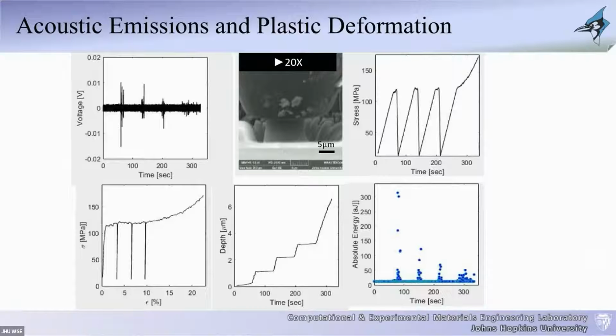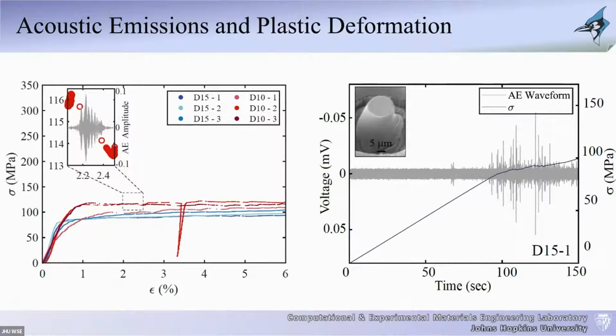But the neat thing with this type of experiment, let me show you a close-up of one of these experiments. So these are basically just representing different stress strain curves. If you look at one of these stress strain curves in a very small spot here where there was some type of drop in the stress as you were loading, what you're seeing here is a very close-up of this part right about there. And you can see that the acquisition rate of the load displacement is basically each one of those dots. Every circle represents feedback that you're getting from your actuator. But with the acoustic emission, this is what we're seeing during that event.